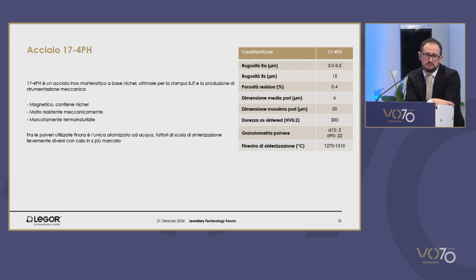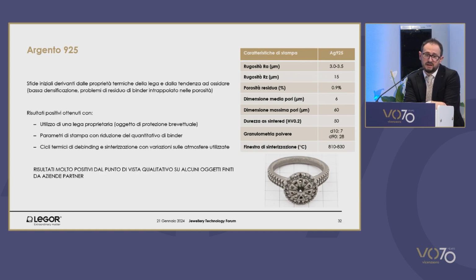We have also used a hard steel. It is a nickel-based steel, 17-4 PH. This has been our working bench for powders that have been produced with water atomization. There were no problems during the printing phase, with the exception of a more marked shrinkage on the Z plane, something we still have to sort out.